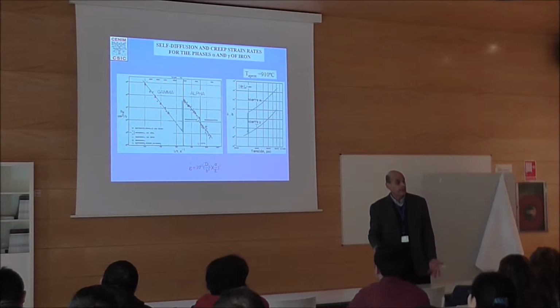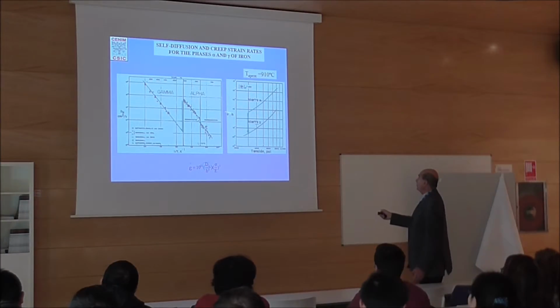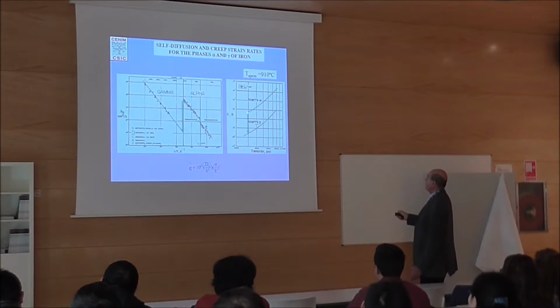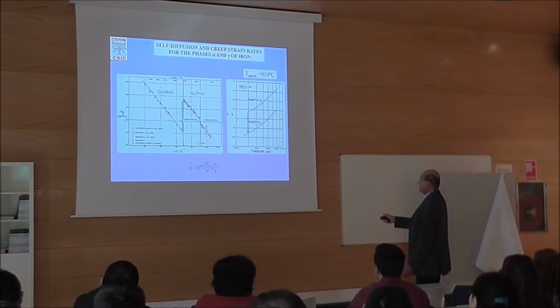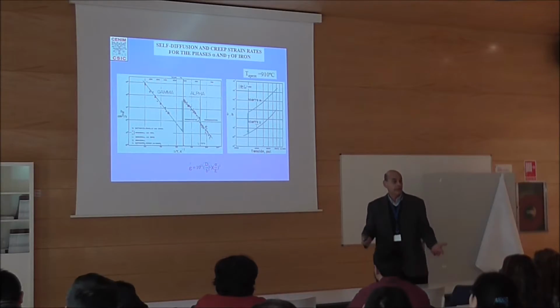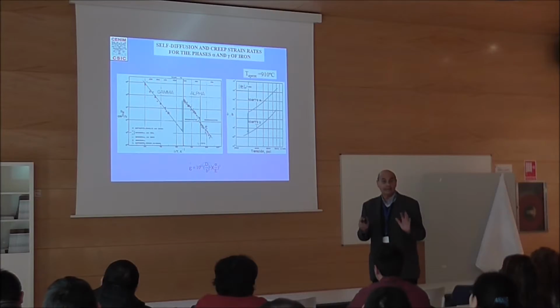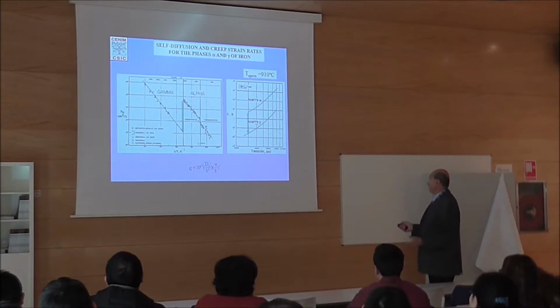And now we make an experiment in creep, and we go first to the alpha iron, and you will have this, and then you change the temperature, and you go to gamma iron, and you have exactly the same change in strain rate as this. It means for us that this is proportional to the diffusivity, lattice diffusivity. We are talking about lattice diffusivity. Difusión en volumen in Spanish.